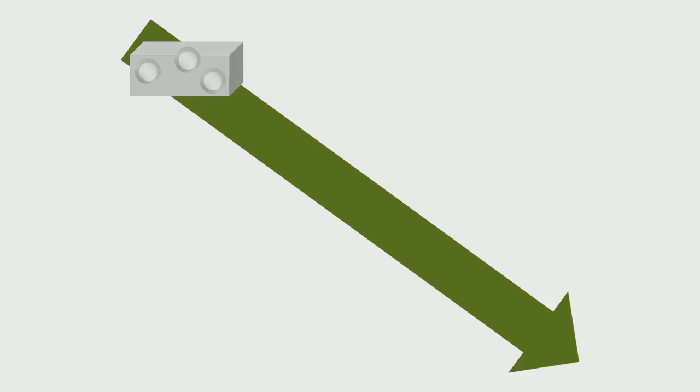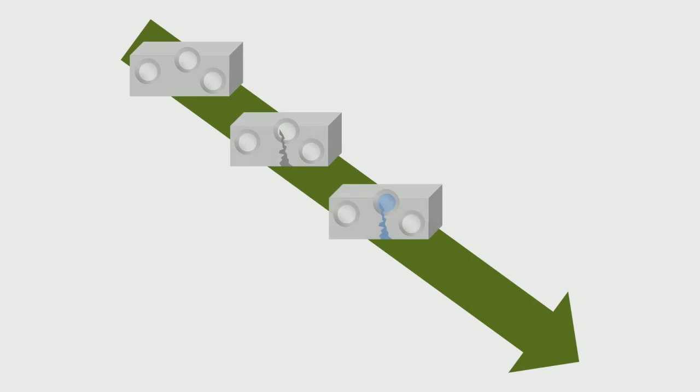Superabsorbent polymers are located in the pores of the concrete matrix. When a crack appears in the concrete, it goes through the pores with superabsorbent polymers. As water enters into the crack, it is absorbed by the particle. The particle swells and blocks the crack.